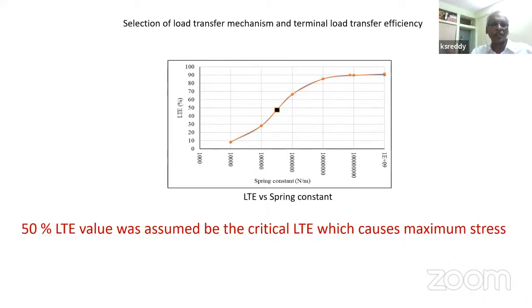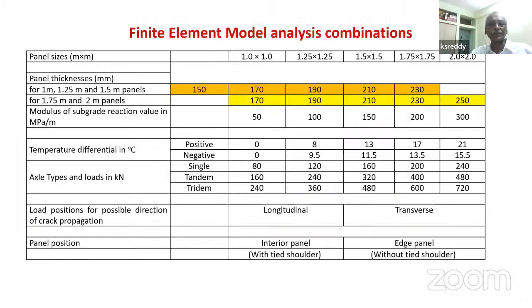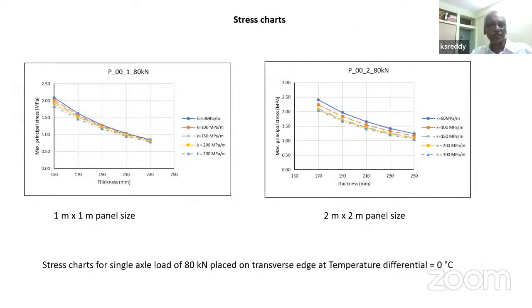Typically, we will get much greater load transfer efficiency from one panel to another. It would be of the order of 70-80% throughout the service life period. But assuming that there is going to be disintegration of these joints and the load transfer efficiency gets reduced, there will be more bending stresses as well as more stresses on the foundation. These are typical combinations that we consider.